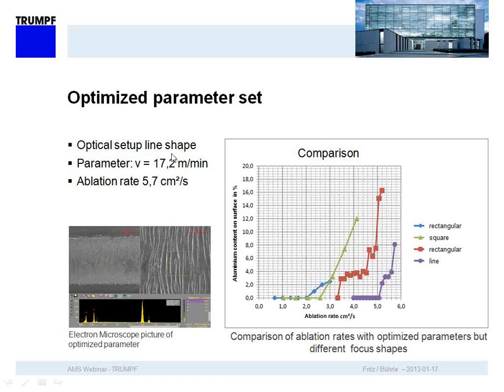So we did this optical setup with the line shape. We had very good parameters at around 17 meters per minute of ablation rate. And here we can see a little photo of an electron microscope picture, how clean the surface gets with the optimized parameter set.